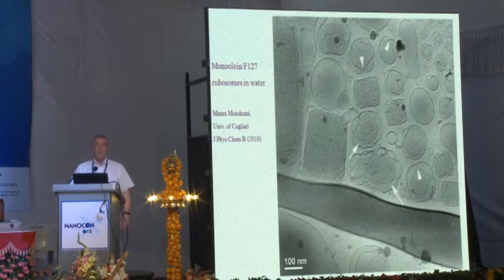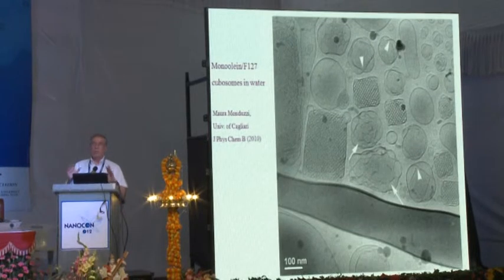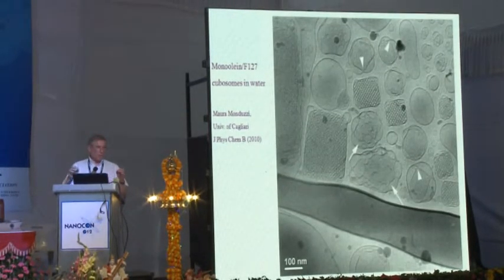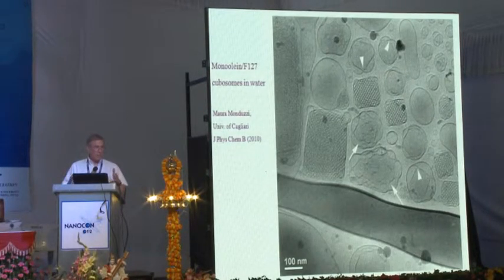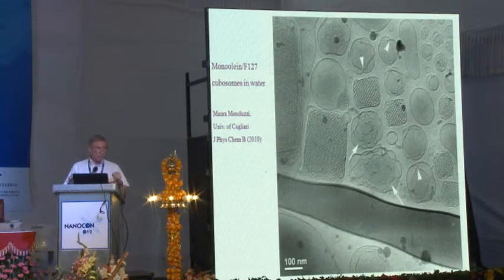Okay. So basically, I will just describe it in words, and I will not go into details because we have no time for that. You take a liquid drop, you put it on a support film which has holes in it, and you make very thin liquid films out of this liquid drop. The film is about 20 to 300 nanometers thick. Because it has such a very high surface area to volume ratio, when you quench it in the right cryogen, for instance, for water, we use liquid ethane at its freezing point, the cooling rates, and we have measured it, are indeed 10 to the 5th degrees per second. And the samples, as you can see on the screen here, are really vitrified.